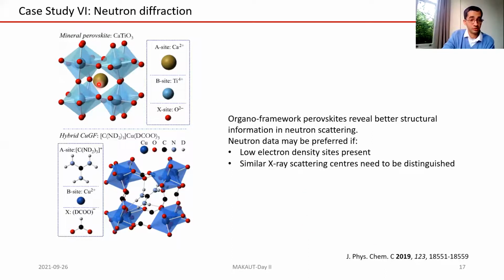Coming back, if you have something like this, you can use X-rays. But what these authors did was that they used a different kind of structure, which had this copper system, and a guanidinium structure, where the framework was made of guanidinium, which contained oxygen, carbon, nitrogen, and deuterium. Now, the problem here is that if you have these kinds of low atomic number elements, such as carbon, nitrogen, deuterium, X-rays don't really diffract that well. The reason is the way X-rays interact with matter. If high electron densities are present, X-rays diffract well. But if they have low electron densities, a low number of electrons, then X-rays don't diffract that well. But with neutrons, which are neutral, the diffraction physics is the same, whether they're neutrons, X-rays, electrons, and so on and so forth. And neutrons can be used to find information about the structure.